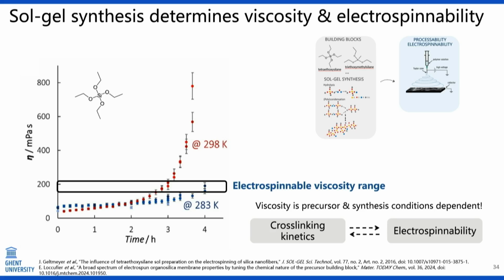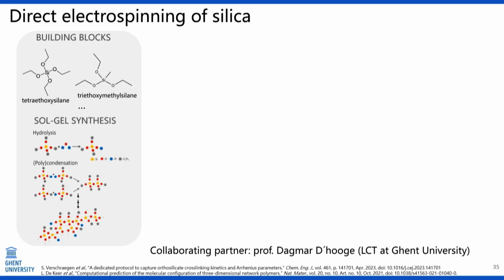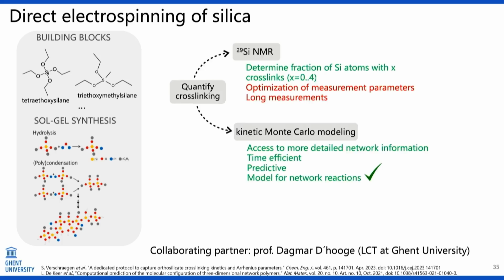So we wanted to know more about the cross-linking kinetics, as more insight in the cross-linking kinetics would help us to understand the spinnability performance. And that's where the collaboration with Professor D'hooge came in. We studied the cross-linking kinetics by quantifying the cross-linking. You can do it experimentally by NMR. That already gives you the fraction of cross-links of the silicon atoms.